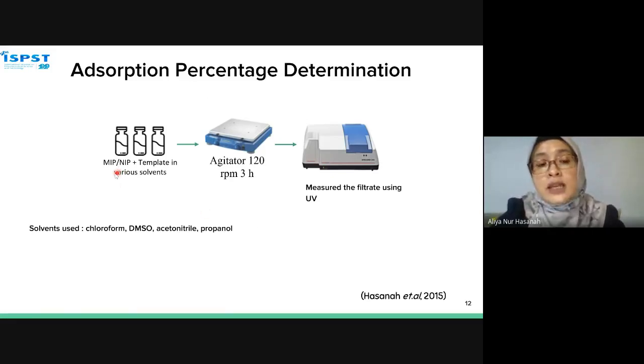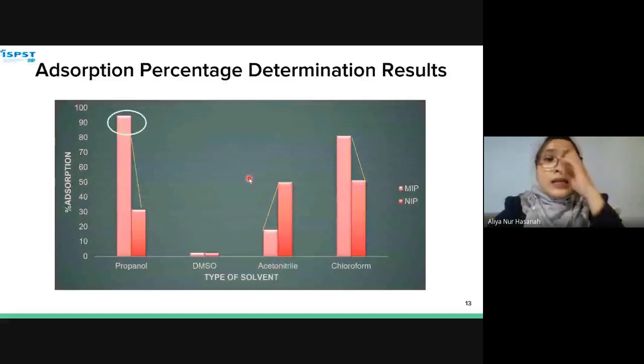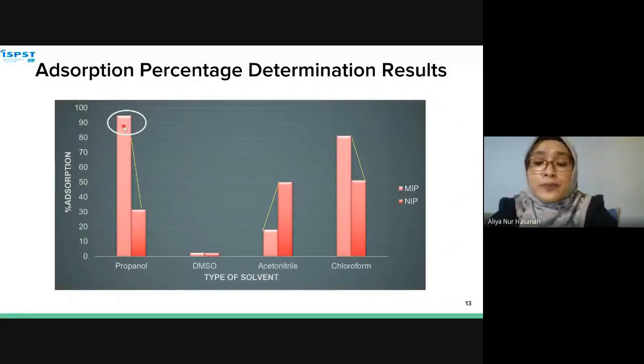From this one, the procedure is that MIP or NIP is mixed with the template in various solvents. We are using chloroform, DMSO, acetonitrile, and propanol. We agitate at 120 RPM for 3 hours and then measure the filtrate using UV. This is the result. From the result, we can see that propanol is the solvent with the highest adsorption percentage of diazepam. This has a linear correlation with other research, where usually the porogen used in the synthesis has the highest adsorption percentage.